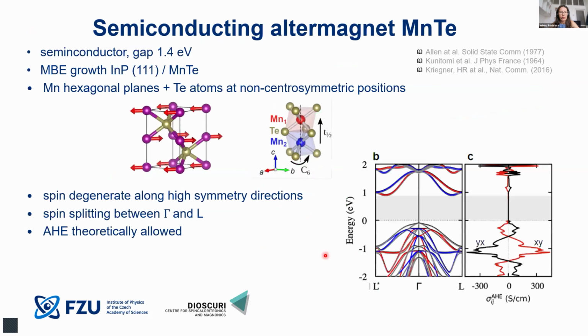So let me start with maybe one of the most explored materials. It was also discussed yesterday, the semiconducting manganese telluride. It was introduced already, so I will just very briefly say that it's a semiconductor. Our samples are MBE grown on indium phosphide. These hexagonal planes of manganese are surrounded by tellurium cages, and the calculations show this characteristic splitting, and therefore the consequent anomalous Hall effect is allowed.